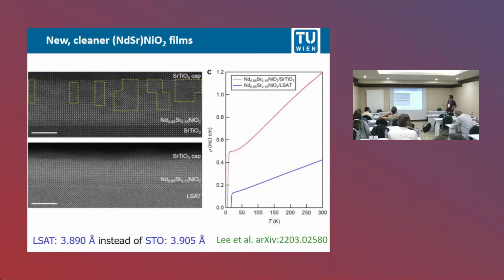Now, why are these films much better? The old films had these Ruddlesden-Popper stacking faults, so there's a lot of disorder, and the new films don't have this disorder. This way, the resistivity dropped by a factor of 3, and the Tc was also enhanced by, depending very much on the doping, a factor of 4 or 2 or whatever. So you see here, cleaner films are now in excellent agreement with our theory. These films are grown on LSAT instead of STO, but you see here within 1% the lattice parameters are the same, and that is all that enters in our calculation.